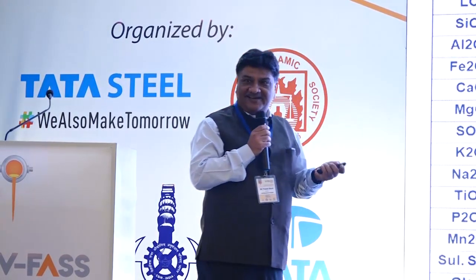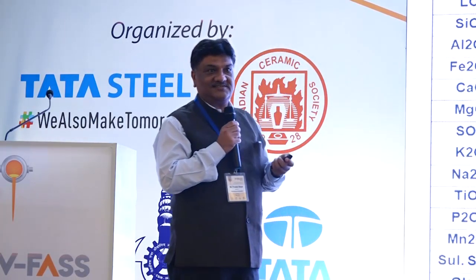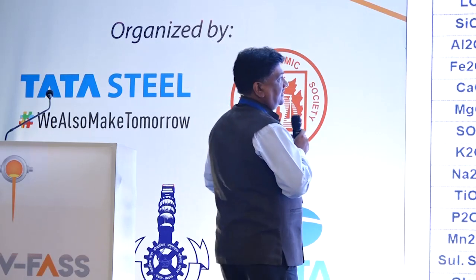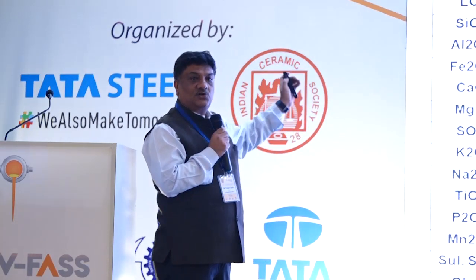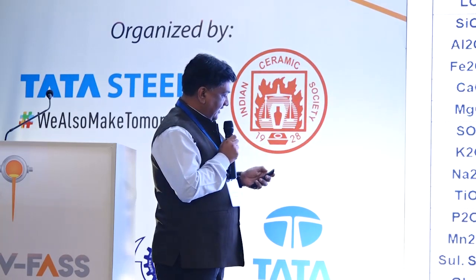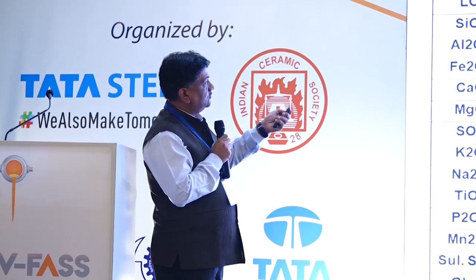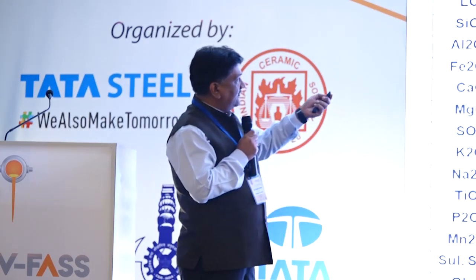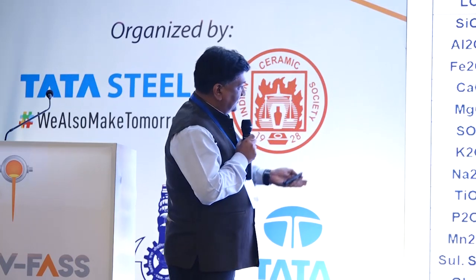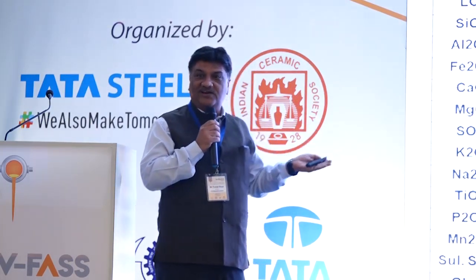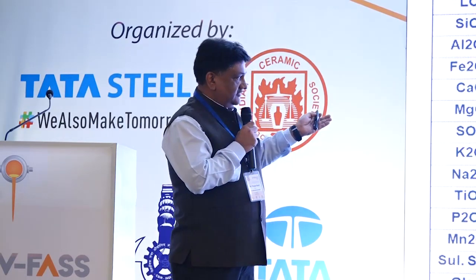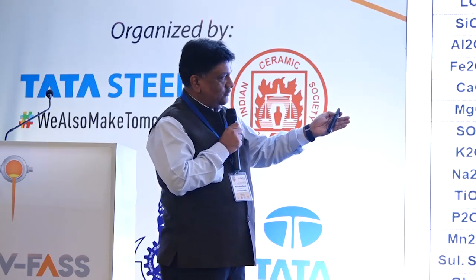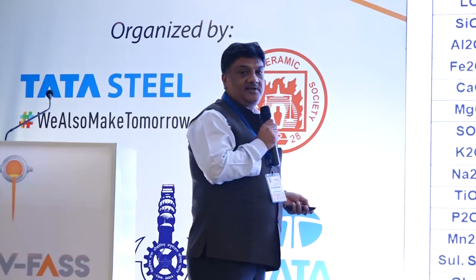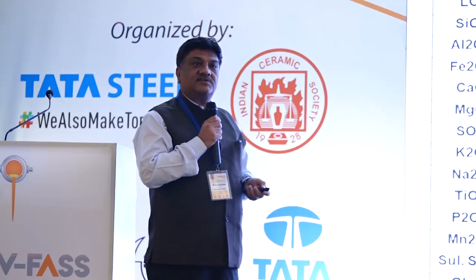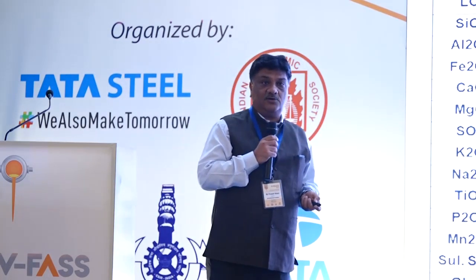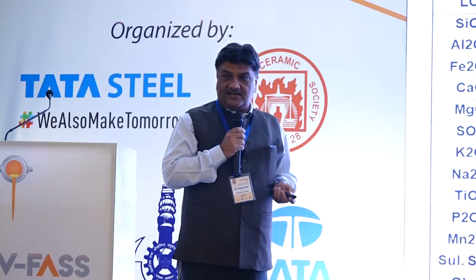However, the LF slag is available on a campaign basis. So if Tata Steel will provide it to us on a consistent basis, definitely this can work well. This is the combined analysis of BF slag, LD slag, and LF slag. If you look at the combined analysis with the replacement ratio of 98 to 1 to 1 between the BF, LD, and LF slag, all the chemical properties required for utilizing it as a slag are matching. So that is what we can do, and I can say that 1 to 2% of BF slag or clinker can be replaced using LF and LD slag. So these are the possibilities attempted, of how the LD and LF slag can definitely replace the clinker and BF slag.